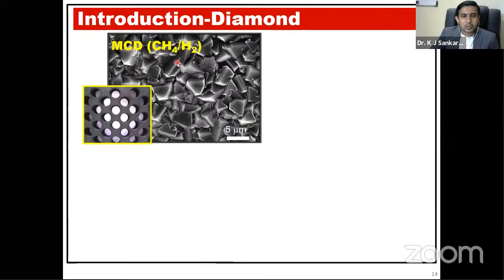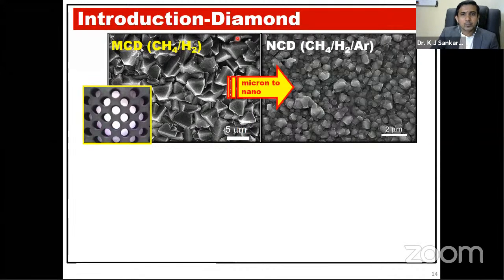You can see that when you use methane and hydrogen plasma, it results in a microcrystalline diamond. We call it MCD. Why do we call it MCD? The reason is that the grain size of this diamond is 5 micrometers. This is the pink plasma I have shown earlier, the purple-like plasma. And when you incorporate argon in the methane and hydrogen, the grain size changes from micron size to nano size.